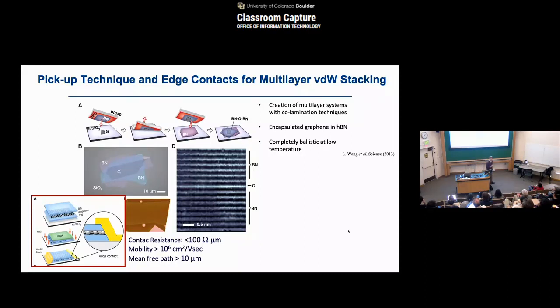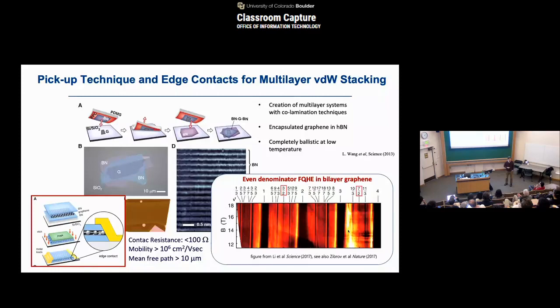Especially in the initial attempt made on graphene in between boron nitride, one can get an extremely high quality electron gas, with the mobility approaching millions or tens of millions. Basically, that is the mobility of electrons you can achieve in the best gallium arsenide crystals, which immediately allows us, for example, by applying a strong enough magnetic field, to see all the fractional quantum physics that has been done in gallium arsenide reappear in graphene. In some cases it is even stronger and more robust, simply because you can put much more carrier density into graphene with high magnetic field. Sometimes repeating very similar physics that appears in gallium arsenide, but in a robust way, provides us another advantage to using this type of 2D materials for the study I'm going to share.